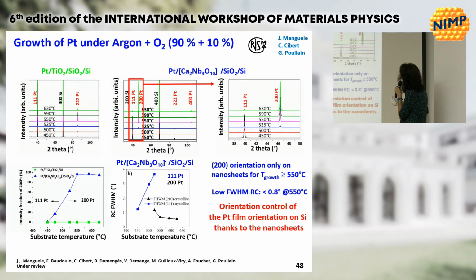But with the film on nanosheets, after 500 degrees, we can see the appearance of the 200 direction. Here is a zoom of this area. Clearly, after 550 degrees, we have a 200 orientation. And what is also really interesting is that the width of the rocking curve is also very low, lower than 0.8 degrees. So here we can have an orientation control of the platinum film thanks to the nanosheets.